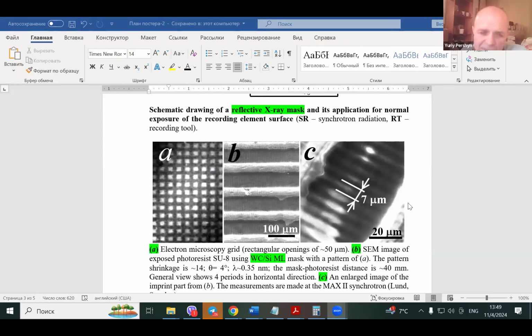On figure A, it is shown electron microscopy grid, which we use to form absorbent pattern on the surface of the tungsten carbide/silicon multilayer, through which we deposited tungsten layer, absorbent tungsten layer, 2.5 micron thick.